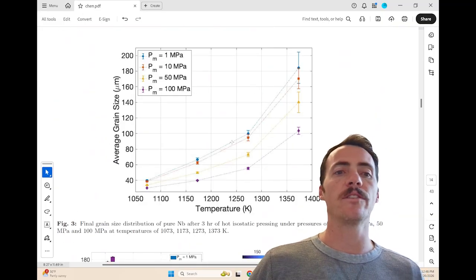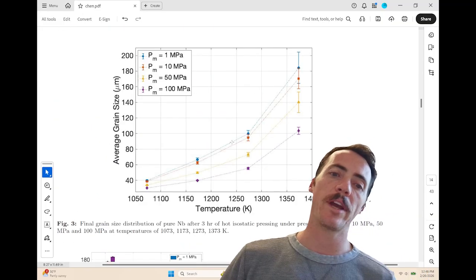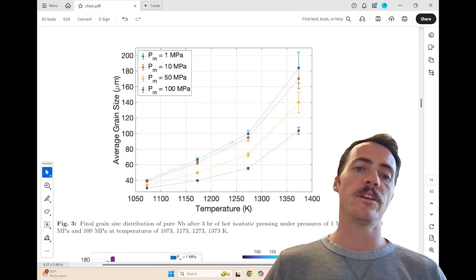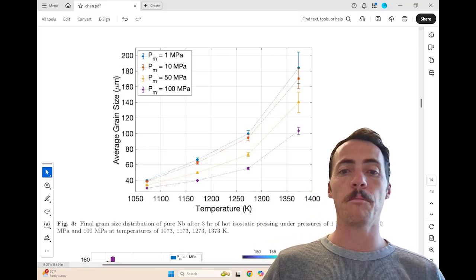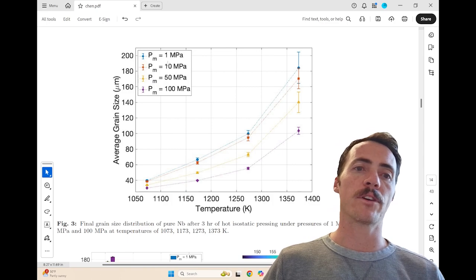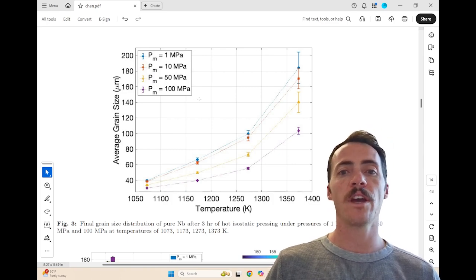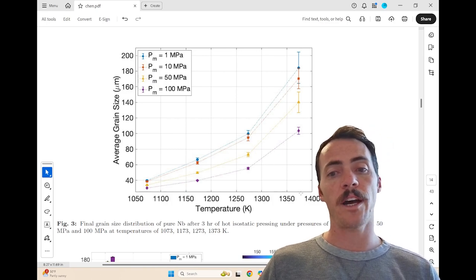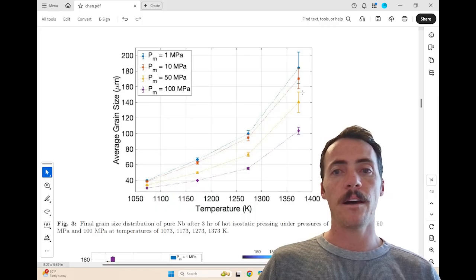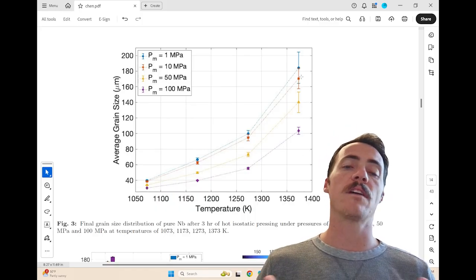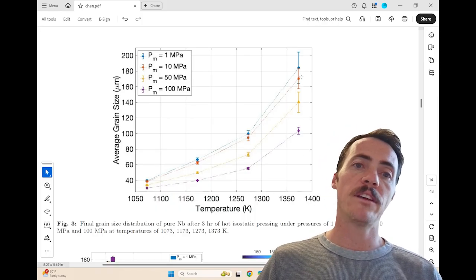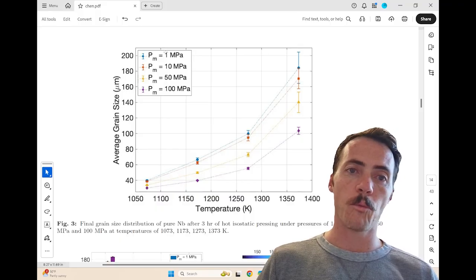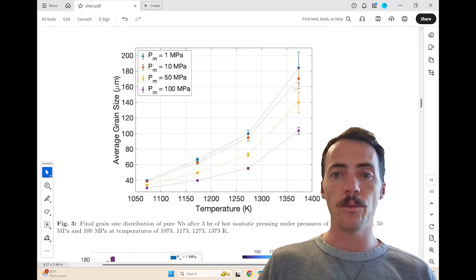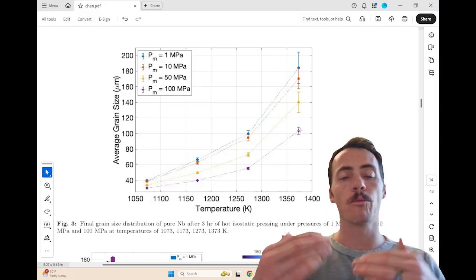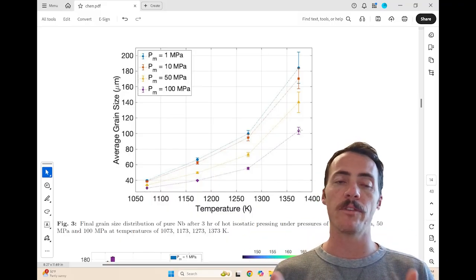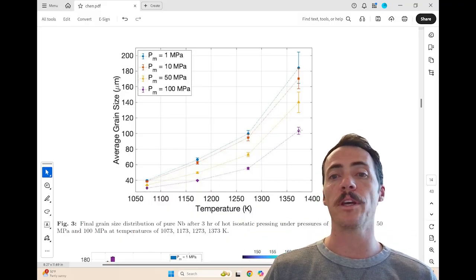Maybe first let's take a look at this graph. This shows you the average grain size as a function of the hipping conditions. On the x-axis, it's the hipping temperature, and then in the different marker colors, you see the different pressures used. And you can see that, as you go to these really high temperatures for hipping, you can get significant grain size increase, right? But you see with the control of pressure going from 1, 10, 50, 100, if you turn up the pressure, then you can reduce that grain size. And so there's a bit of a trade-off available for you in your hipping conditions.